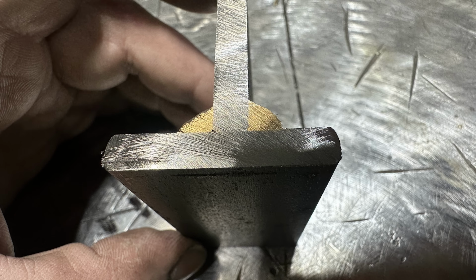So this is what a proper braze should look like, at least the one on the right. The one on the left has what would be a lack of fusion where it bridged over the root of the joint. That can be pretty typical with bronze brazing, simply because if your heat input and travel speed aren't exactly right, or you're trying to put down too much material, the heat doesn't get far enough in the joint to melt that material down in there.